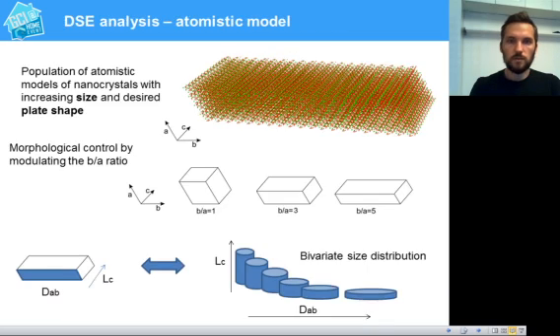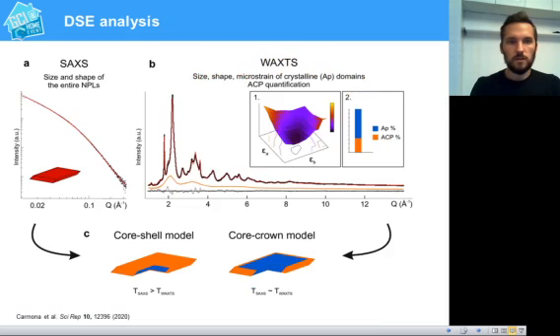So at first we built an atomistic model of nanoparticles at increasing size and desired shape, and from this atomistic model we simulated the scattering pattern for the small angle and wide angle X-ray scattering, and we refined several parameters to fit the experimental data. So the analysis of the small angle X-ray scattering data provides the information on the size and shape of the entire nanoplate, whereas the analysis in the wide angle provides size and shape of the crystalline fraction together with the microstrain information and the quantification of the amorphous phase.